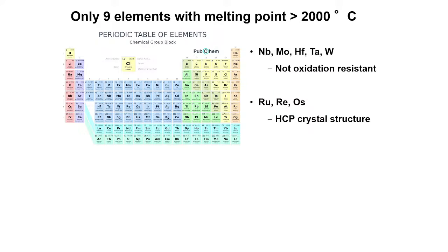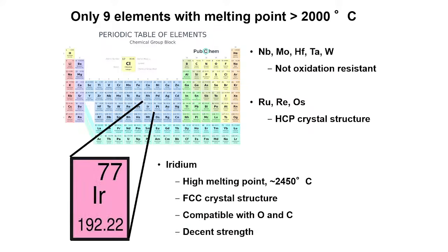These elements, niobium, moly, hafnium, tantalum, tungsten, these are the refractory BCC alloys. They are not oxidation resistant, and so they will not survive. Ruthenium, rhenium, and osmium are HCP crystal structures. So with HCP, you know that it has brittle fracture. So that kind of leaves only one element, iridium. It has a high melting point, about 2450 C. It has the FCC crystal structure, so it's ductile, relatively, with some exceptions I'll talk about. It's compatible with oxygen and carbon, and it has decent strength.